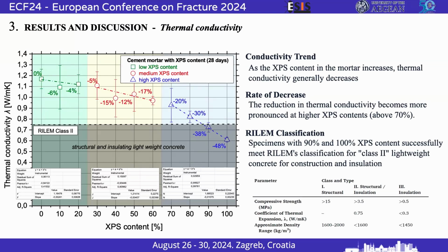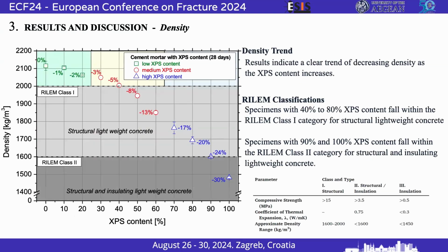So with the use of the XPS, we can alter the matrix and make a new type of material that can actually have insulating properties. Here you can see the results of the density. Of course, with increasing the XPS content, the density is decreasing. Again, according to RILEM, for the specimens with 90 and 100% replacement of sand with the XPS, this material falls in the RILEM 2 category. It can be characterized as structural and insulating.